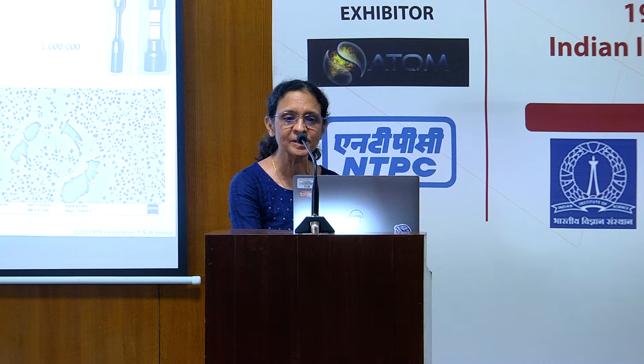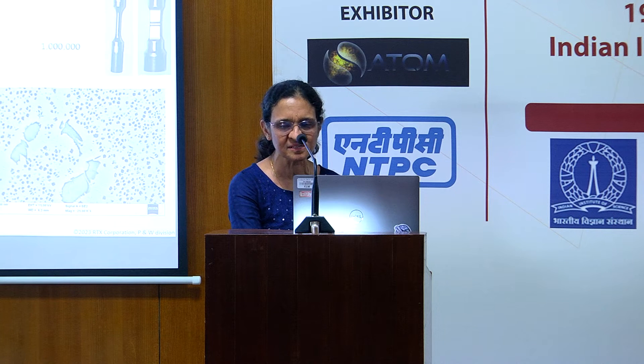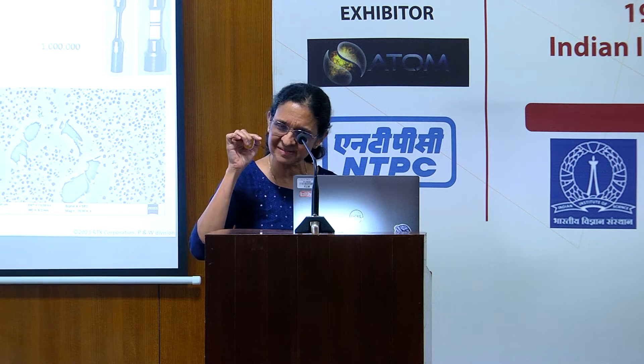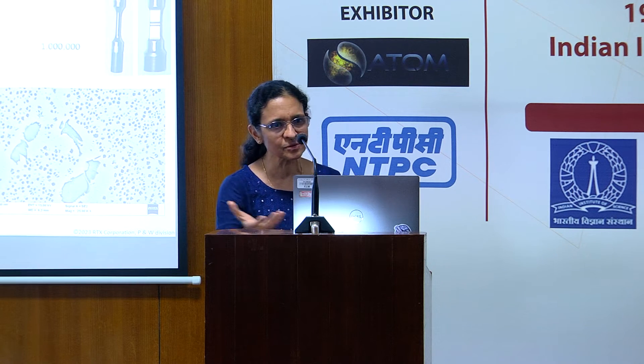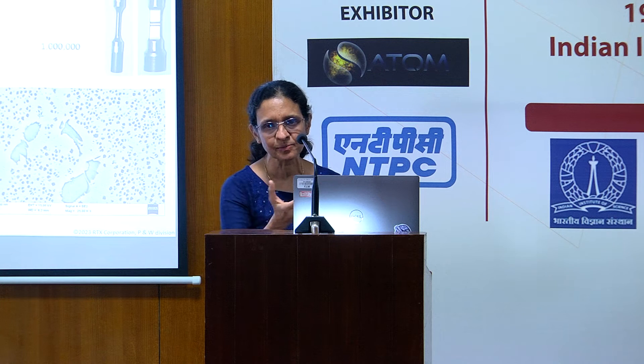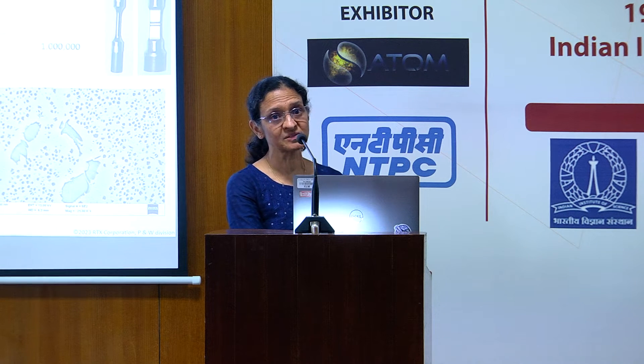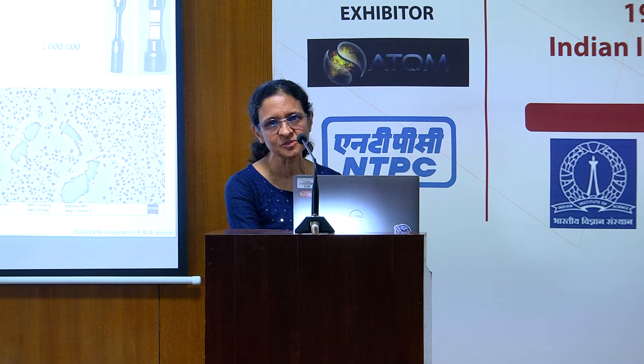If you do a quick laboratory study — both in-situ corrosion, by which we corrode it and then do a low cycle fatigue test, or we do the low cycle fatigue test separately — we don't have any laboratory, at least in India, where you can do the test while continuously fluxing the salts with sulfur. So these are all more static experiments, but it's the best we can have. And you can see a clear fatigue debit, even in these experiments which don't perfectly replicate actual conditions in an aero engine.